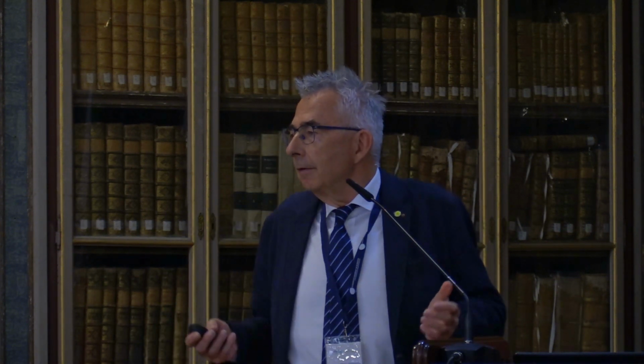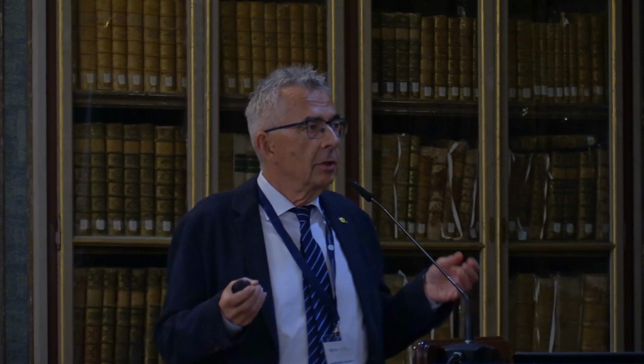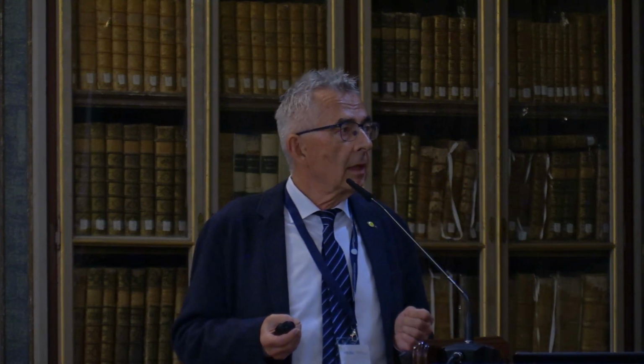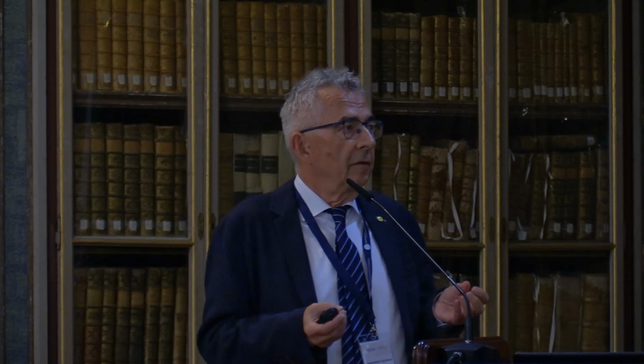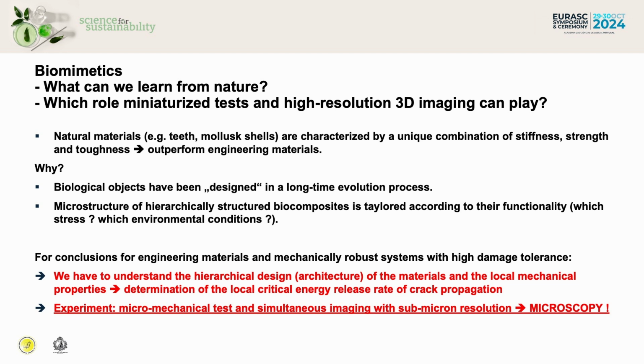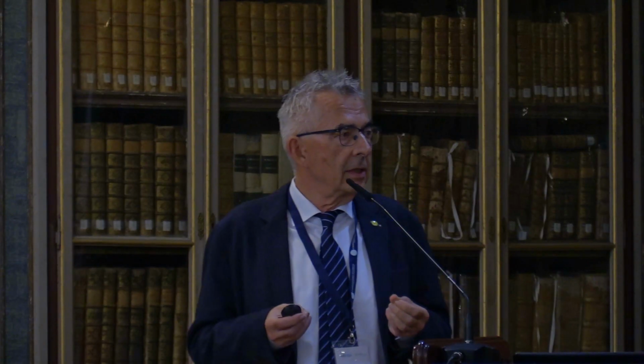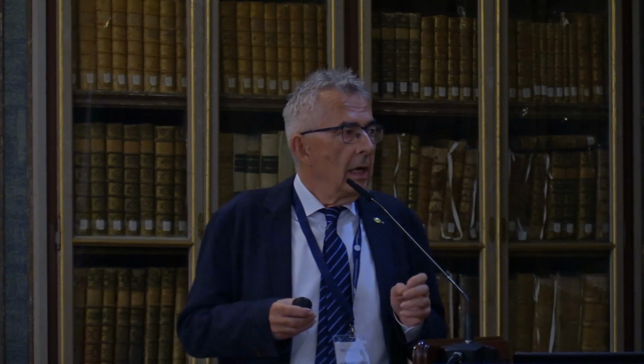Of course, why? We know nature had a very long period of time to design such a structure in the evolution process, and we don't have so much time for our engineering process. And also the microstructure of such biocomposites is tailored according to the needs that nature has. For conclusions for engineering and mechanically robust systems with high damage tolerance, we need a better understanding of the design of the materials and the mechanical properties. And what we have to do, we have to determine local materials properties, and we have to understand the processes at a crack tip. We really have to go into the nanoscale.